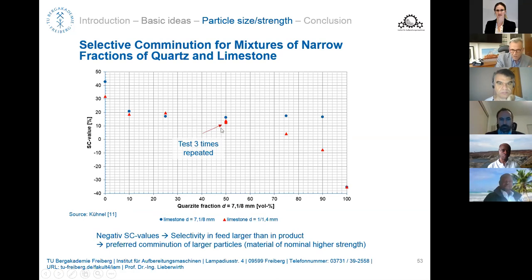So we can see a very similar result looking at the limestone and quartzite comparison. We add 10% of limestone to the quartzite. We see that both fractions are similarly broken, so we don't have much change. But then we see that the limestone breakage is reduced, and we have essentially an increased breakage of the quartzite fraction. Here we have a point where we repeated the test, and we could show that the repeatability of the test is quite nice.